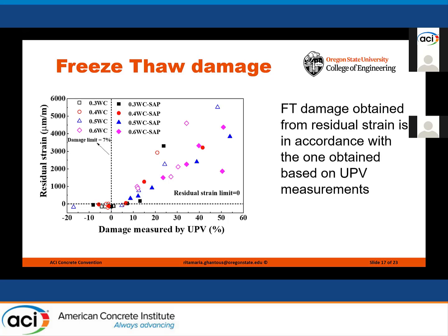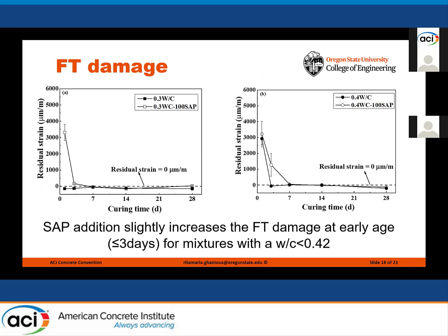So if we go ahead and look at that, and we start with mixture with a low water to cement ratio below 0.42. So we have 0.3 water to cement ratio on the left, and 0.4 water to cement ratio on the right.